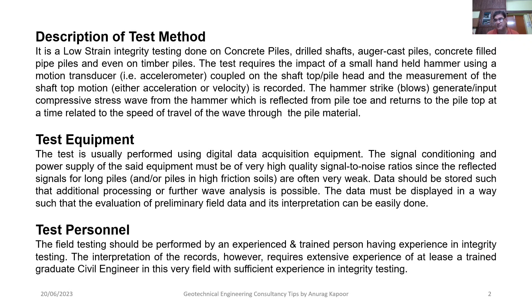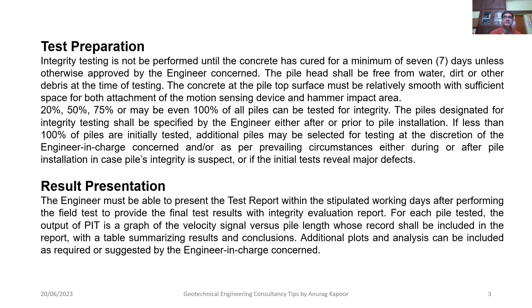In a future lecture I will explain the two methods in detail with figures. Regarding test preparation, integrity testing is not to be performed until the concrete has cured for a minimum of seven days, unless otherwise approved by the engineer in charge. The pile head shall be free from water, dirt, or any other debris at the time of testing so that real-time data and accurate results can be obtained. The pile top surface must be relatively smooth with sufficient space for both the motion sensing device attachment and the hammer impact area.